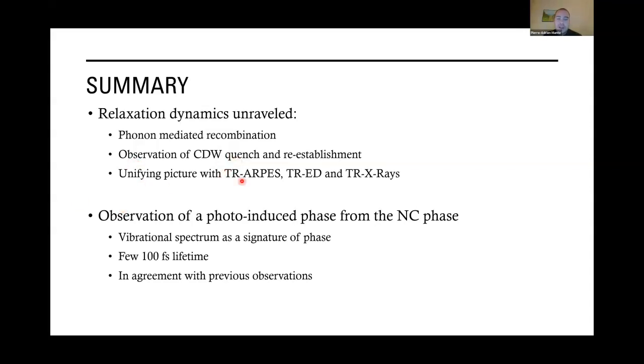And what is nice is that our results are at the same time coherent with the ARPES data and also with techniques that are more sensitive to lattice dynamics, such as X-ray and electron diffraction. The second project concerned the existence of a photo-induced metastable phase from the nearly commensurate phase. We were able to demonstrate that the vibrational spectrum of a phase is really a signature of this phase, so we can use this as a probe of a phase transition, like has been done in previous experiments. And we highlighted the existence of a metastable phase that has a lifetime of a few hundreds of femtoseconds at room temperature, in agreement with the predicted existence of a phase that can be driven from the nearly commensurate charge density wave.